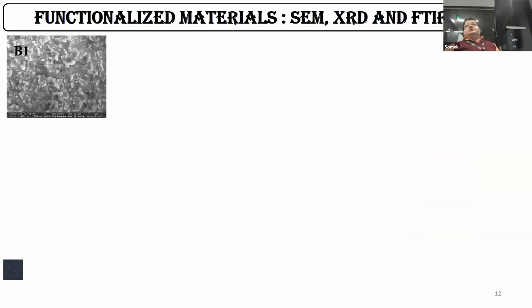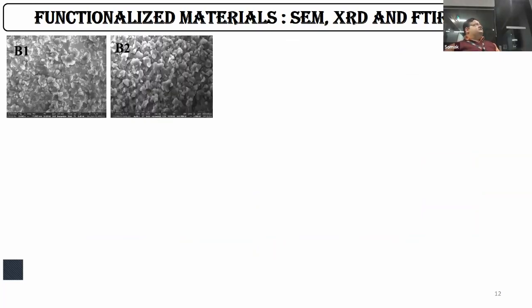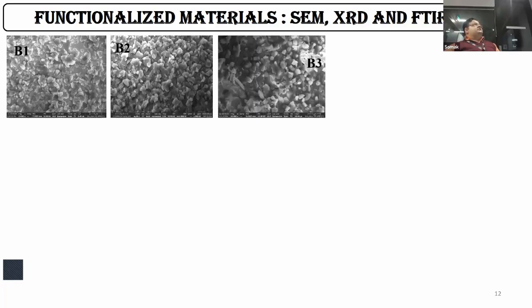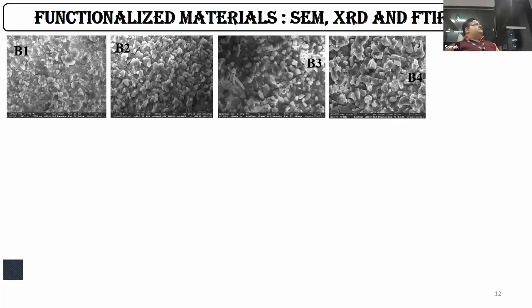Once we had the beads, we continued with the characterization. The first one is to see the morphology, and we can see rough and rugged structures on the surface. The first is the control, that is the pure polymeric bead, followed by B2, consisting of undoped polyaniline. Then we added doped polyaniline to polyethersulfone, and the final one is polypyrrole.